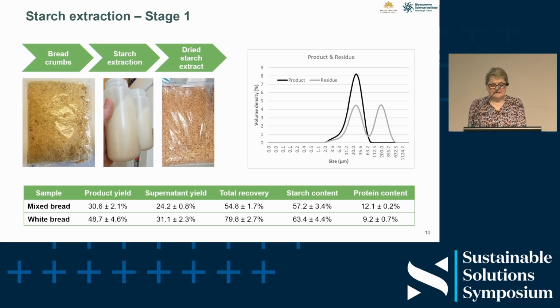And the supernatant, basically that's when they mix the starch with water, spun it in a centrifuge, and the liquid at the top, that's actually quite important as well. We found out down the track. We were originally just planning to use the starch in the thermoplastic starch, but the supernatant, when we added that together, that added to the total recovery and yield, and we used that down the track as well.